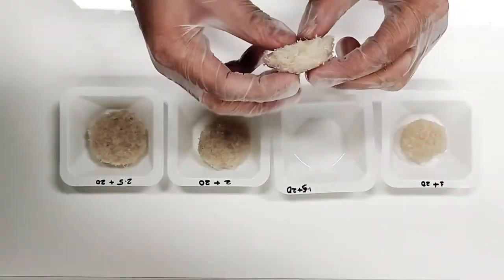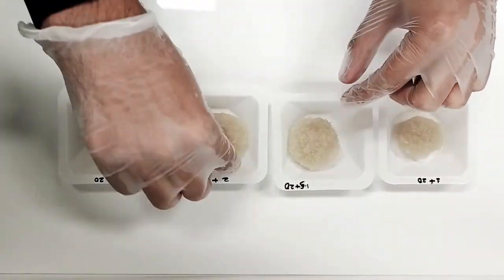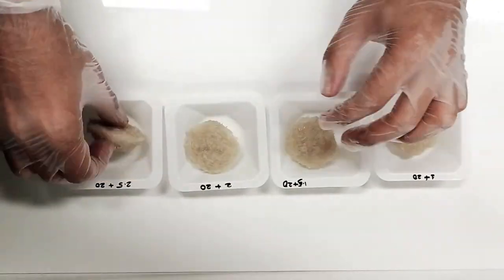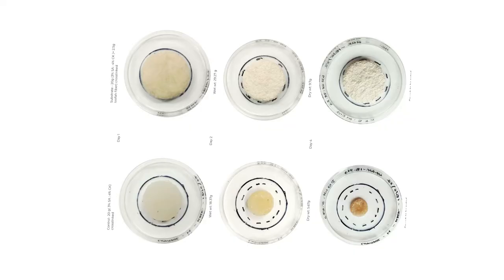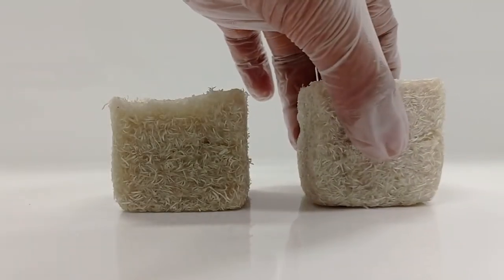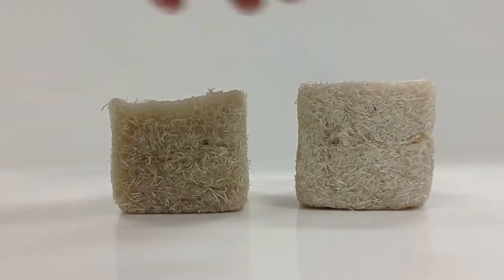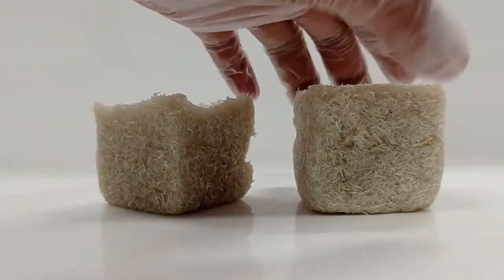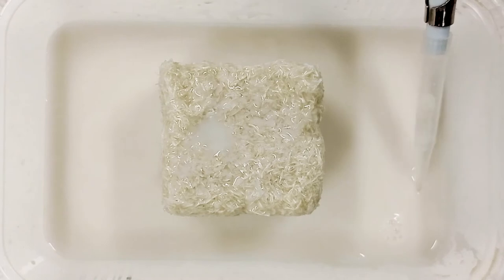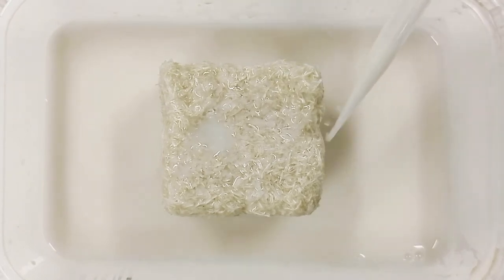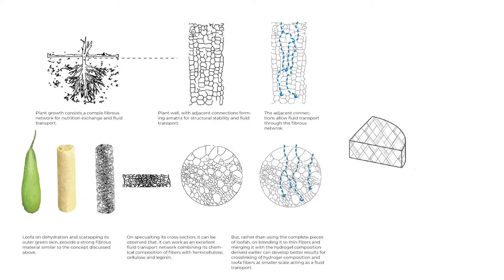Through extensive research, a novel hydrogel-based substrate material was developed for architectural application and appeared promising with less shrinkage and better strength compared to a regular alginate-based hydrogel. This was done by introducing plant-based fibers with a chemical composition of cellulose, hemicellulose and lignin that allowed uniform fluid transport of the cross-linking agent, ensuring a stable 3D matrix of hydrogel composite.